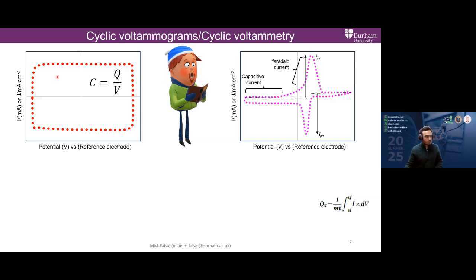I can estimate the capacitance or the capacity, depending on the behavior of the material. If it is a pure EDLC or pseudo capacitor, then it is preferred to calculate the capacitance rather than the capacity. That's why the capacitance should be reported rather than the capacity, because calculating a capacity for this material will be somewhat misleading, because you're not dealing with any Faradaic reactions to deal with the charges, rather the farads. So you can calculate the area under this whole curve, and using this expression, you can convert it first into specific capacity and then divide it by the total potential range, and that's how you can get the capacitance.